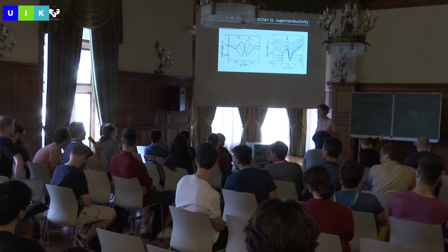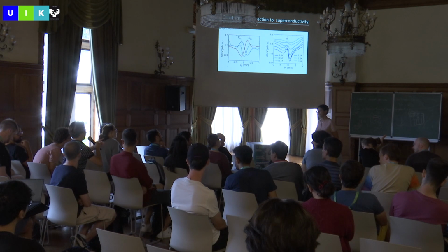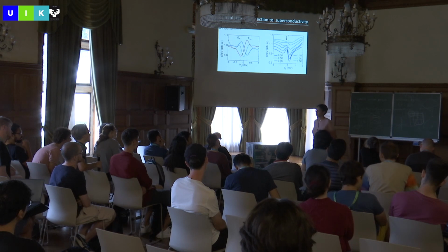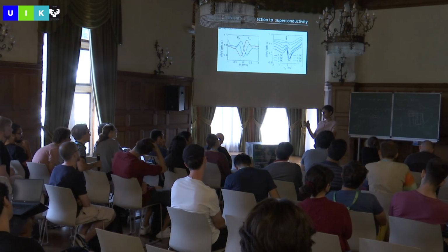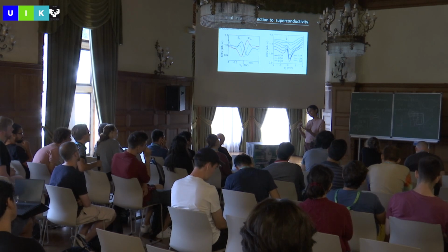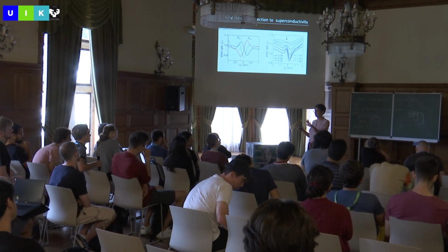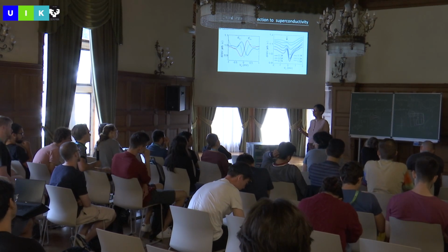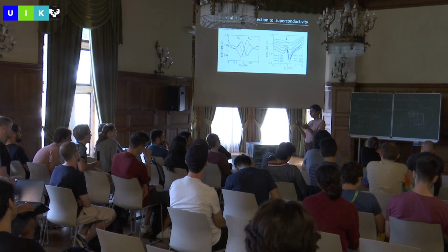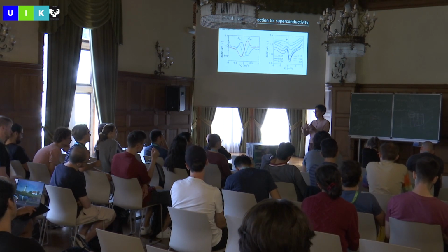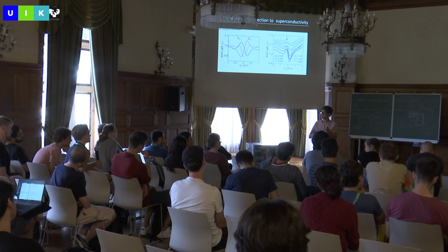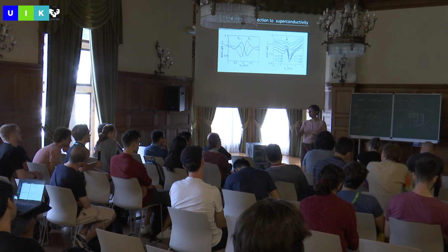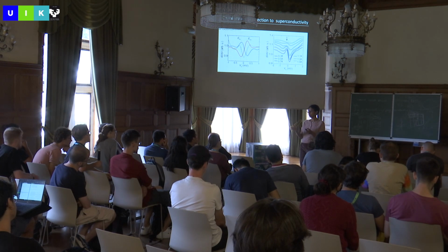I guess it's very unlikely, but is there a chance that what you interpret as a domain was actually a 1D defect, like a dislocation or something? Of course, the nice thing about STM is we can actually see the atoms. We can see that the structure on one side is shifted from the other by half a unit cell. And dislocations also have real space distortions, so whatever dislocation you want to cook up, we can ask what that real space distortion is supposed to look like.